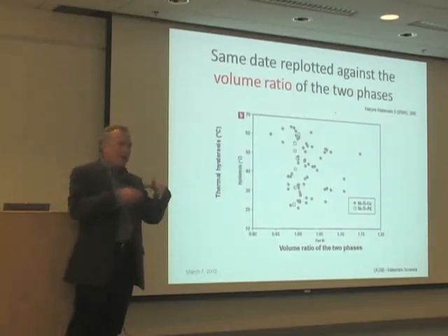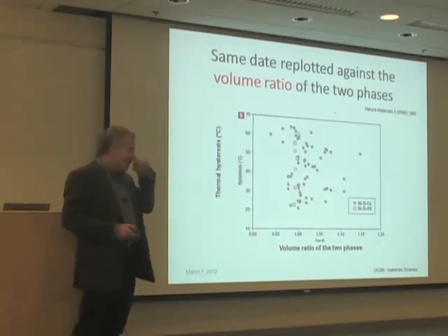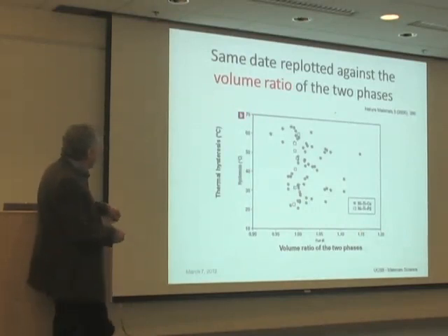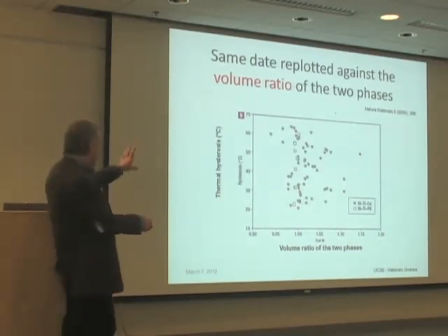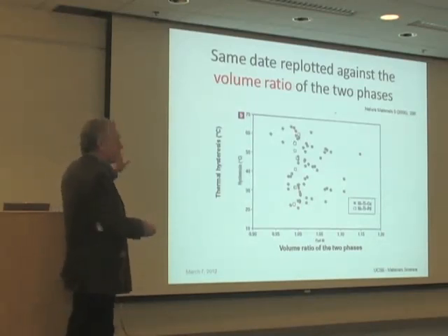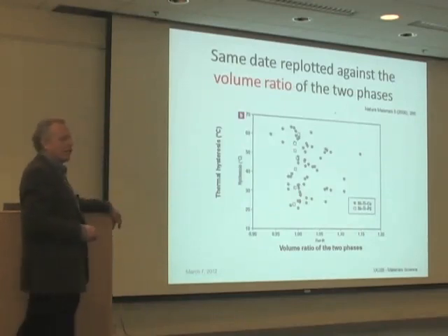But if you plot the same data versus the volume ratio, at volume ratio 1, you get some of the smallest hysteresis and some of the largest hysteresis. This is actually a subset of the data that was done earlier. But there seems to be no correlation with the volume ratio of the two phases. It correlates very well with the middle eigenvalue.